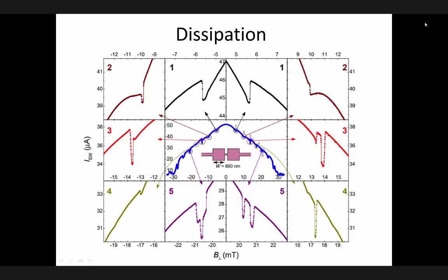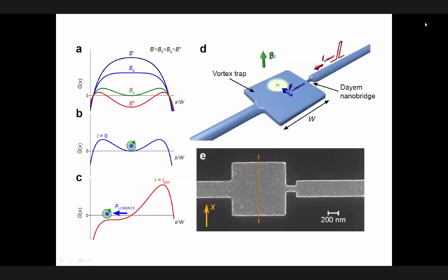Yes, you see, this is vortex fields. In practice, these barriers are not fully symmetric because of what people usually call the magic word pinning. This can explain everything, but it means that it's always easier to push a vortex to one side.